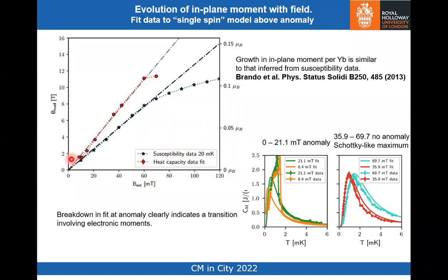What we find, the red data. So we find this linear increase in the size of that moment, which is very similar to the linear increase that was previously observed by Brando in this paper. So that piece of physics is essential, that as you apply a field in plane, there's a growth of the in-plane moment on top of whatever antiferromagnetic order that you have.